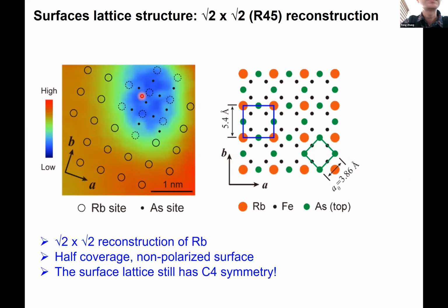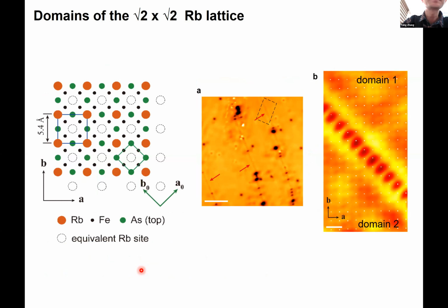In the vacancy, we can resolve the arsenic lattice beneath the surface rubidium lattice, because its lattice constant is exactly the lattice constant of this material. So we can say that the surface lattice is indeed root 2 by root 2 reconstruction. The rubidium is at half coverage, so it is a non-polar surface. Here it is important to notice the surface lattice is still C4 symmetric. It doesn't break the C4 symmetry.